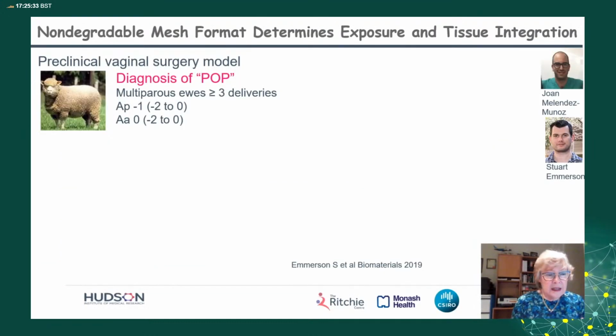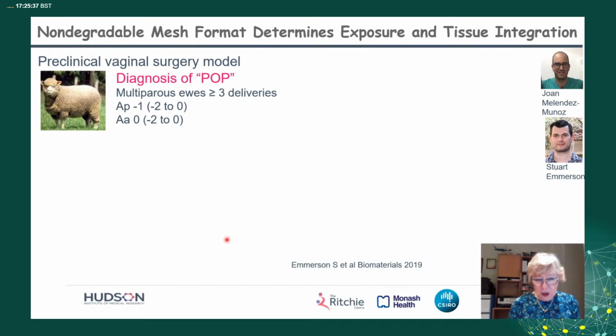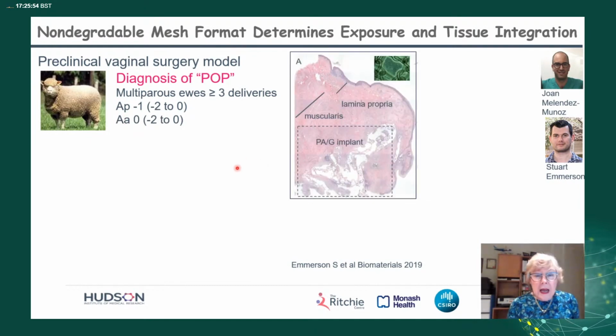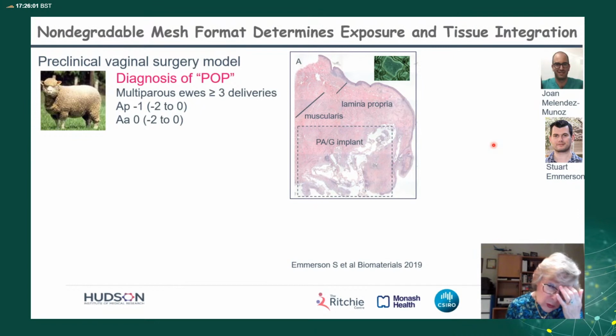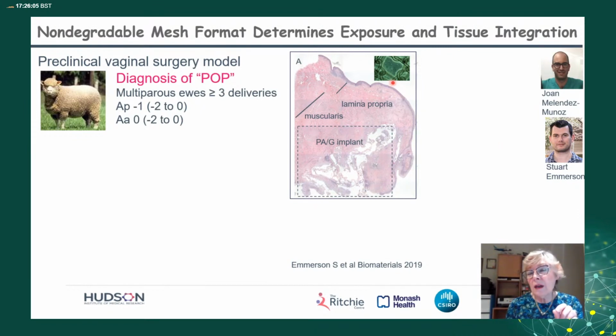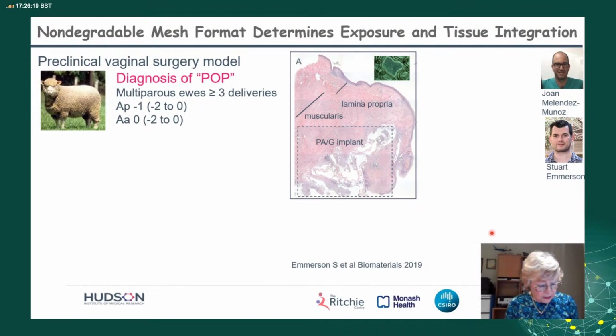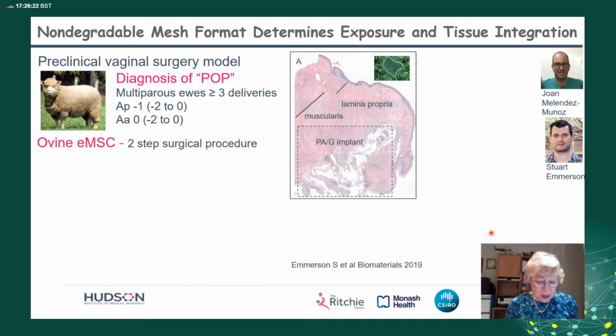Now, to assess this then in our sheep model, we first screened our flock of sheep with POP-Qs to diagnose POP, or vaginal weakness really, and the sheep we examined had Ap median of -1 and Aa of 0. What we implanted in the sheep, this is transvaginal surgery in our POP model. We used the polyamide non-degradable mesh with the cells seeded and grown on a gelatin that filled the pores. Now, to our huge disappointment, when we implanted these into the vagina of sheep, we saw a large number of exposures. So we changed our procedure and made a two-step one.